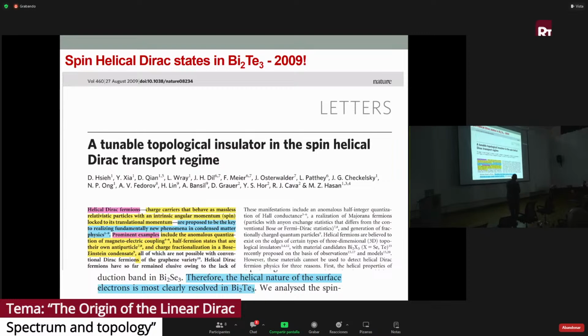It's worthwhile to see the literature back almost 15 years ago, for instance, where they defined the spin helical Dirac transport regime. In this field, people create words, they come and they disappear. This one, spin helical Dirac, essentially says that the spin is perpendicular to momentum, as written here. Charge carriers that behave as massless relativistic particles with an intrinsic angular momentum spin locked to its translational momentum. Okay, so we propose that this is a fundamental new property in condensed matter physics.